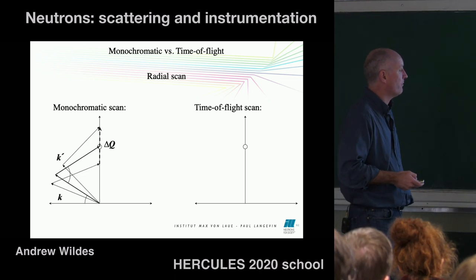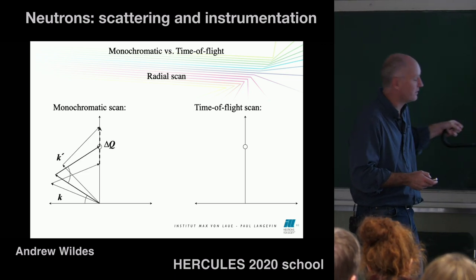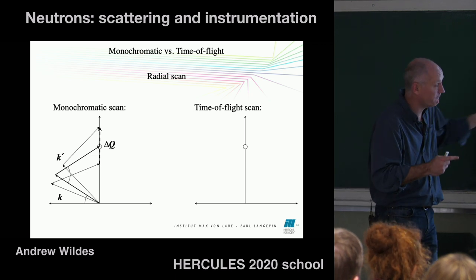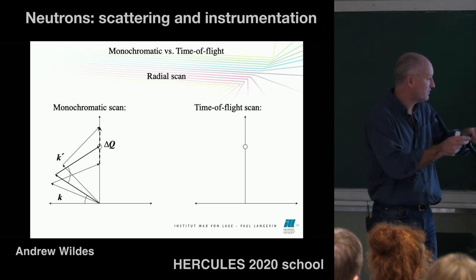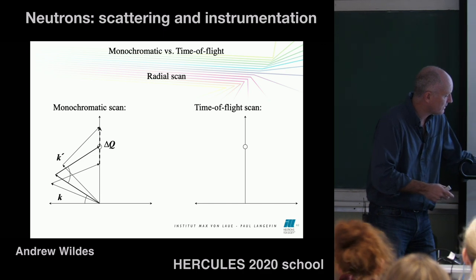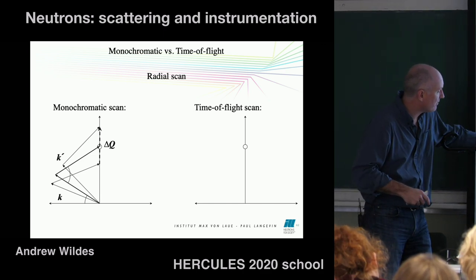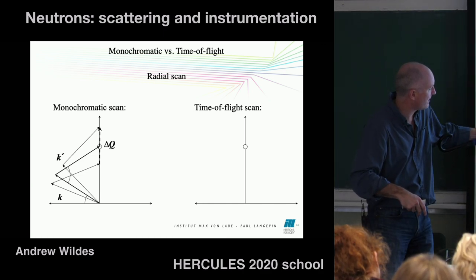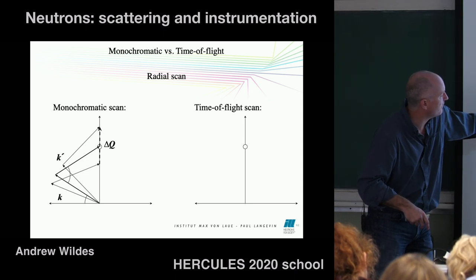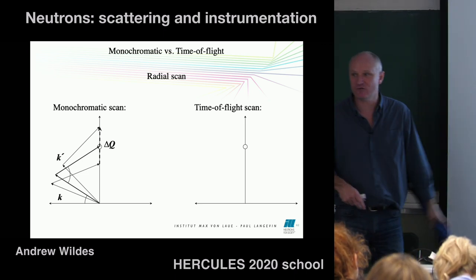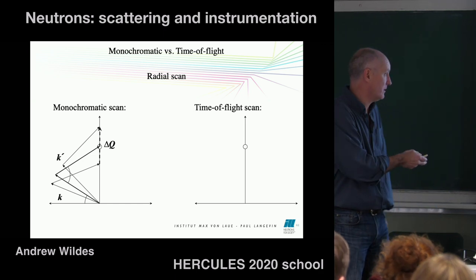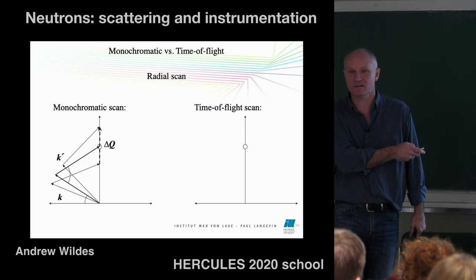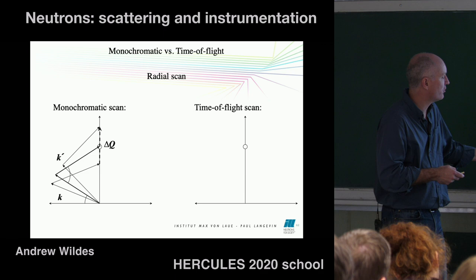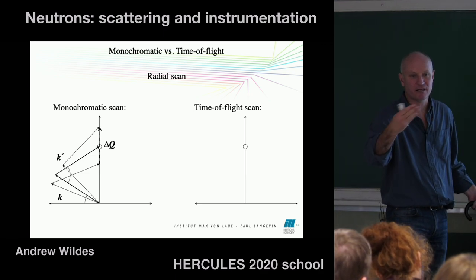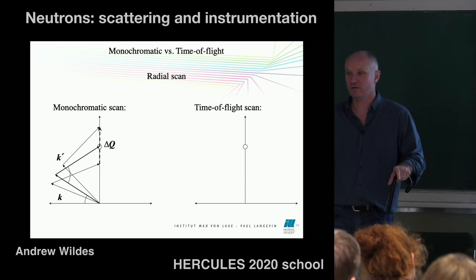If I wanted to do that on a monochromatic scan, my length of k, initial and final, stays the same. And I have to then rotate both my crystal, that's given by this angle here, and I've got to move my detector, which is that angle there. I've got to move them both. And then point by point, I would scan through that trajectory. In fact, that is something that some people might call a theta-2theta scan. You have to increase the angle of your sample by theta. You increase the angle of your detector by 2theta.